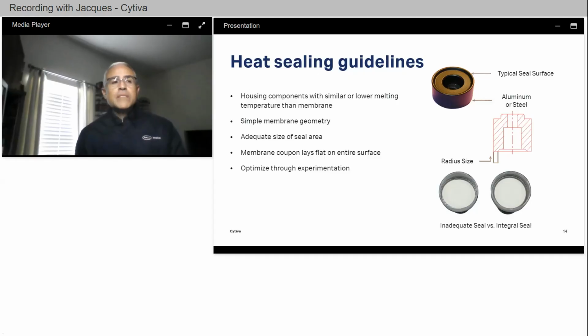The following general heat sealing guidelines apply. A plastic housing to which the microporous membrane is being sealed should have a melting temperature similar to or lower than the melting temperature of the membrane. If it's higher than the membrane's, you may run into an issue where the membrane could be damaged. You should also consider keeping the geometry of the membrane coupon simple, such as a round shape. Having a circular geometry will serve to evenly distribute the stresses on the membrane during the sealing process, as well as during the application use.